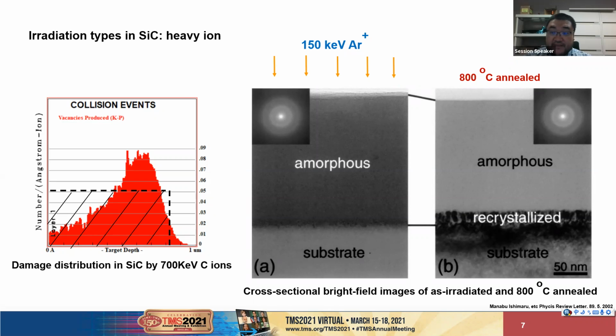But from previous studies, we can see that if you are talking about low energy implantation, you're going to get the amorphous region. And although you can anneal the sample at high temperature to repair the amorphous structure to some extent, it looks like the amorphous structure is pretty stable. So in order to simplify the question, we just average the radiation damage to some extent, which we believe is the easy way to get the radiation damage and correlate it to the thermal property.